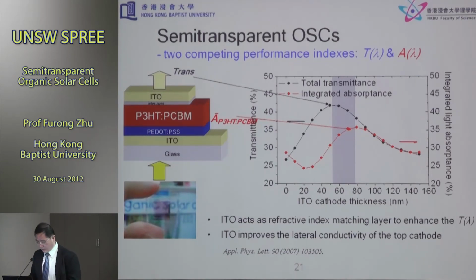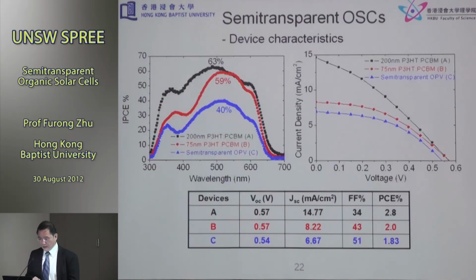This paper was published a few years ago. Here are the parameters, and we have the external quantum efficiency of control devices, which are made on an opaque, very thick layer, around 200 nanometers. And then we reduce the layer thickness to 75 nanometers for the semi-transparent device, because this is where the absorbance spectrum has its first relative maximum absorbance. And then we fabricate a set of devices, and we found that for a complete opaque control device,